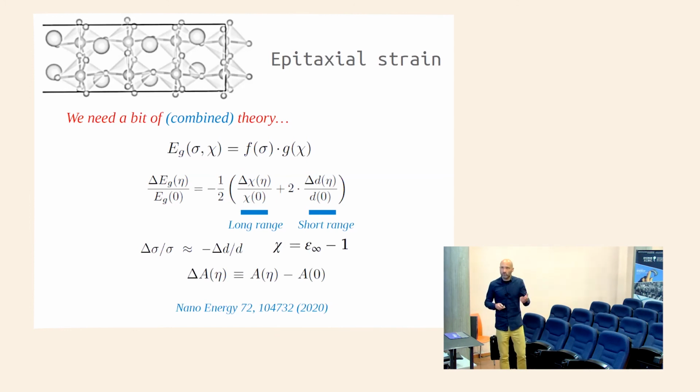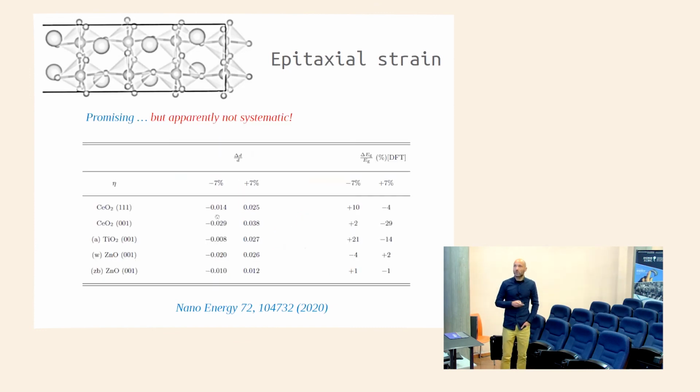It may happen also that the energy band gap may be changed efficiently by changing other long-range or middle-range interactions that have more to do with the electronic screening in the material, right? And since we are working with oxide materials, we know very well that this term here could be non-negligible, right? So, taking this model, we came back to our results.